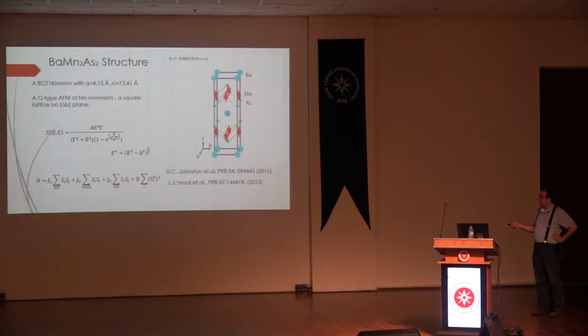Our Hamiltonian is this. As you see, antiferromagnetism is there if the J's are positive. I simply take the positive ones. That is the main effect of the XY Heisenberg antiferromagnetic coupling. This coupling simply produces a kind of frustration on the first one, because this is the next nearest one. This is the antiferromagnetic coupling along the c direction. And this last term is there for defining the LS coupling, uniaxial coupling of single ion anisotropy in other ways.